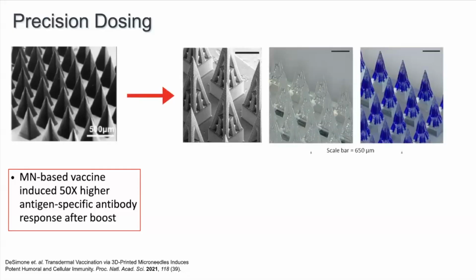And now with these new high surface area needles, we can actually trap liquids into that space in the needles through surface tension. And you can now deliver liquids through a microneedle into the skin. Or more interestingly, you could freeze dry that liquid, lyophilize it in the needles.